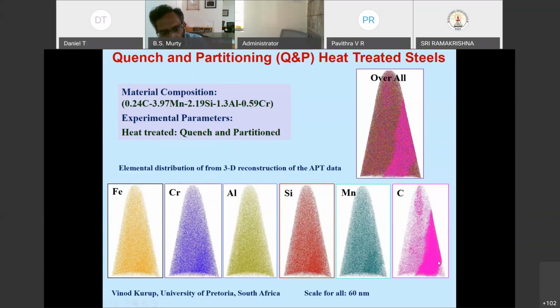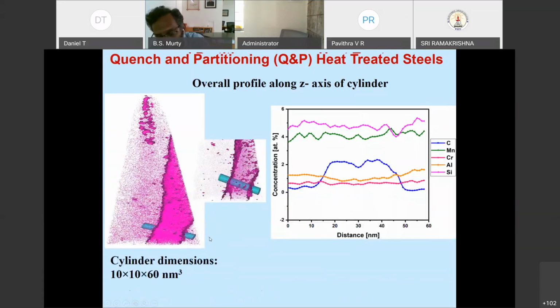So now we can not only see that, we can also do it quantitatively, how the carbon is distributed. For example, you can see in a small region here, of the order of around 20 nanometers, that carbon is getting segregated, and there is a kind of a peak there, whereas the rest of the elements are all uniform. This kind of information can come out. So I can get not only qualitative but quantitative information about any particular phase. What is the composition of the phase at the nanometric level can be found out.